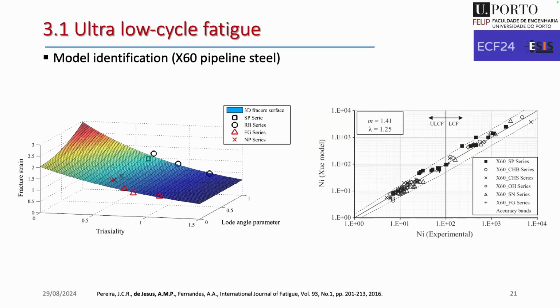So for the identification of the model, we will rely on two sets of tests. First, on the left, we will need to make static tests. Those static tests will be important to define the fracture surface, or the ductility surface of the material, where we have the fracture strain against triaxiality and load angle, and you can see that this is not constant for the material. And then we need to run also cyclic tests, ideally for different stress concentrations or different triaxialities, in order to identify our model constants.